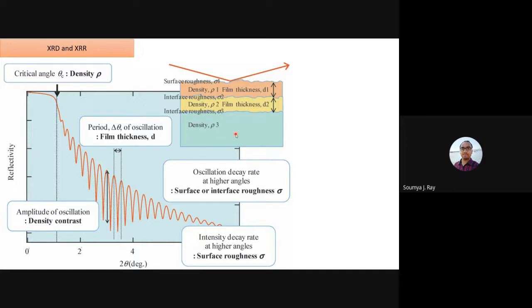And if we imagine that there is more than one layer deposited, then the resulting reflectivity pattern will show us these oscillations. These oscillations could have a varied amplitude, and the periodicity depends on the film thickness. Here there will be a certain angle called the critical angle, above which these oscillations start coming in. This is mostly the substrate effect. This angle is determined by the substrate, and after that you will get these oscillations because of the thin film.